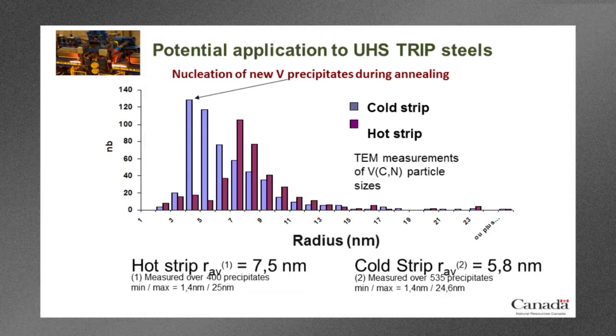Now, we've already measured the volume fraction precipitated in the cold strip. We've shown that it's higher than in the hot strip, and we have a smaller mean radius.